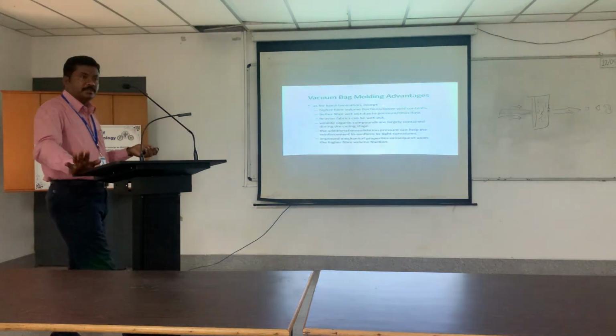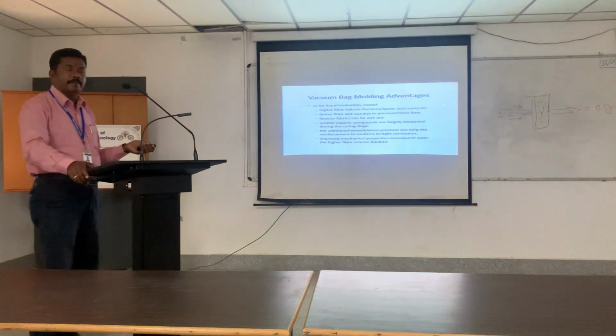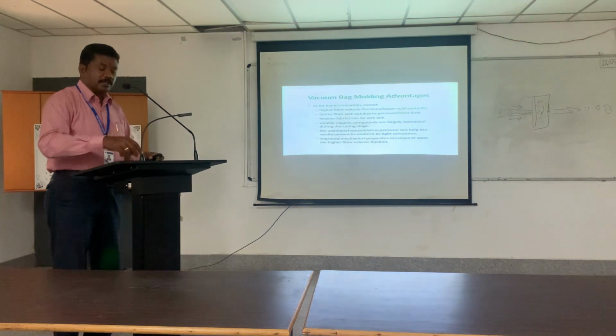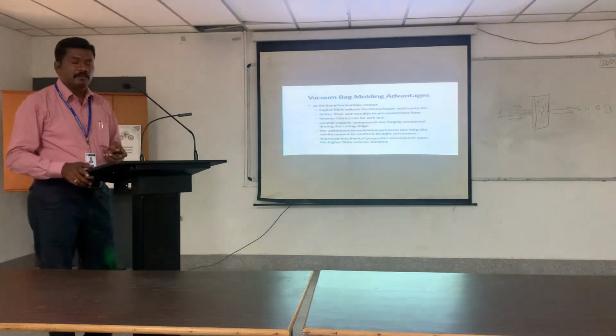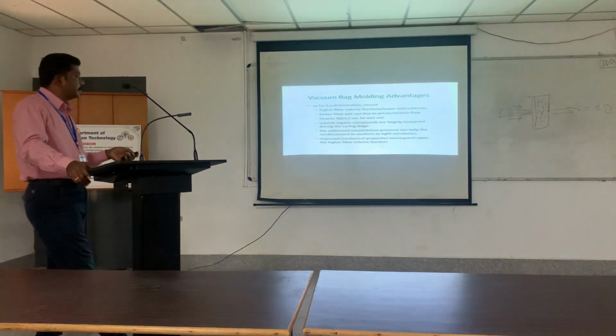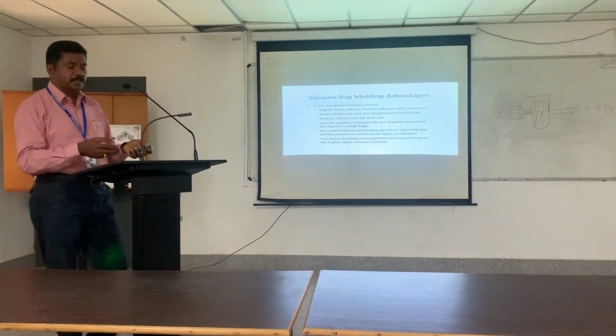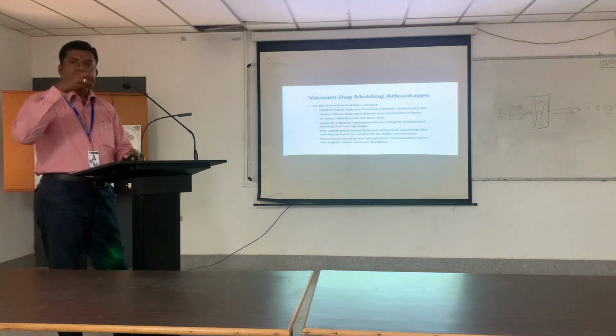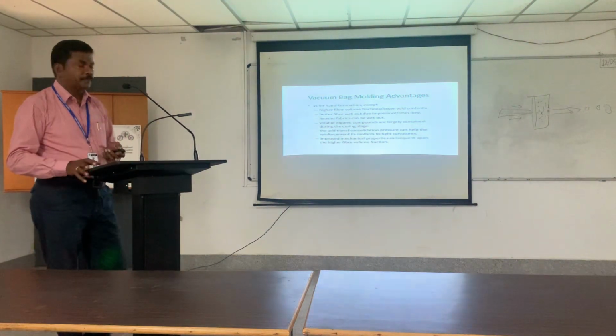Advantages compared with hand layup. Higher fiber volume fraction, that is the obvious purpose of vacuum bag molding. Lower void content. In the case of hand layup, even if you roll out, some of the air bubbles may be left. Those air bubbles will be sucked out during vacuum. Better fiber wet out due to pressure and the resin flow. Even sometimes if some places, say in the 8th layer, fiber is not wet out, if you are sucking from the bottom, the resin will come out and the 8th layer will also get wetted. Heavier fabrics can be wet out.